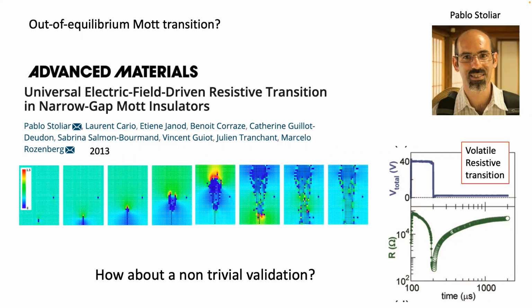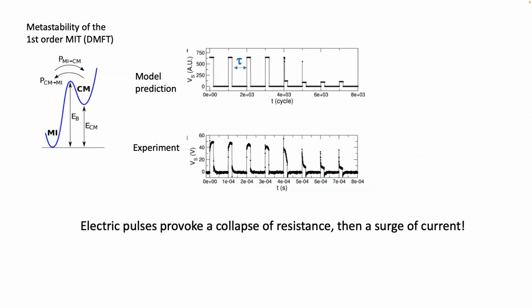Hold on, two seconds. Of course you may say, well, come on, this is just a resistive collapse. It's a percolation. This is not so compelling. So how about a non-trivial validation? Then comes the insight from DMFT. We know that it's a first-order transition with hysteresis. And if we talk about a first-order transition with hysteresis, we talk about metastability, and the famous coexistence of a metal and the insulator.